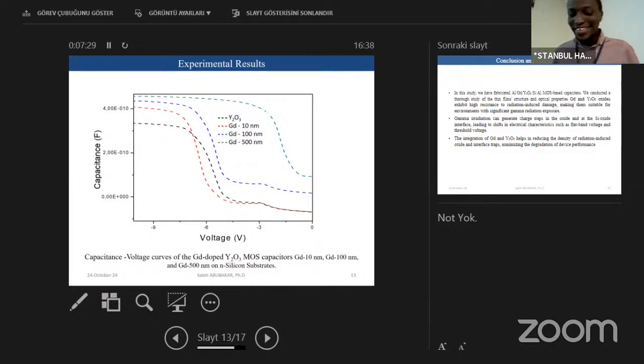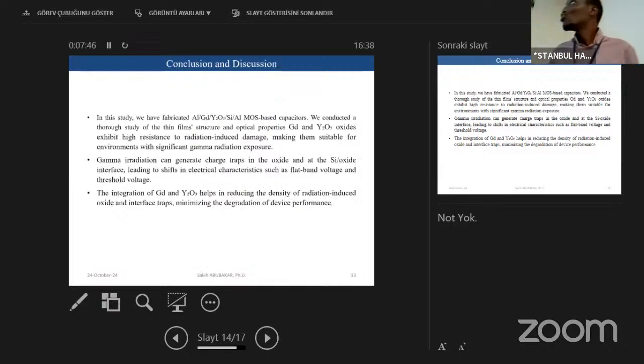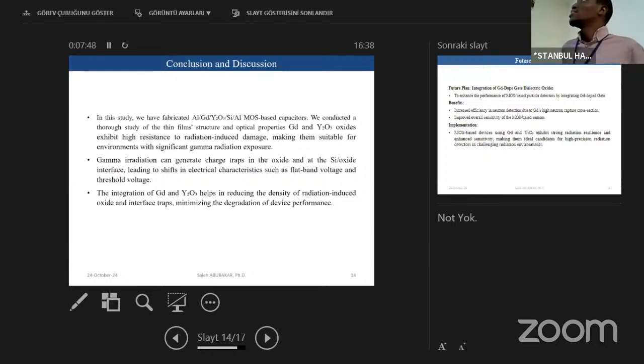So that is what we get for the electrical characteristics, and we are going to publish a comprehensive study about radiation detection and other things about this study in articles or maybe in proceedings papers. So, the conclusion of this material: we were able to see that gadolinium oxide really gives a high reduction of the interface traps between the oxide and the silicon oxide.